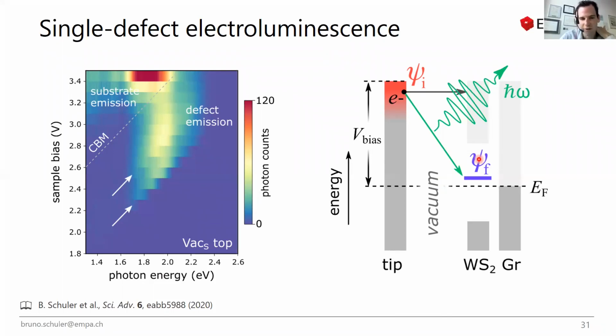That's something fairly interesting with these materials, because through gating, in principle, you can change the Fermi level. But we haven't established these devices yet. It is on the high priority list for us, changing the Fermi level and by that changing the occupation of the charge states. We also want to introduce decoupling layers in between. We are working right now on HBN samples, which are multi-layered, where we can then grow the TMD on top, to really extend the lifetime, and hopefully also study the luminescence coming only from our material and not involving the tip. For instance, injecting straight into the TMD and then looking at the transition. So that's something we want to do.